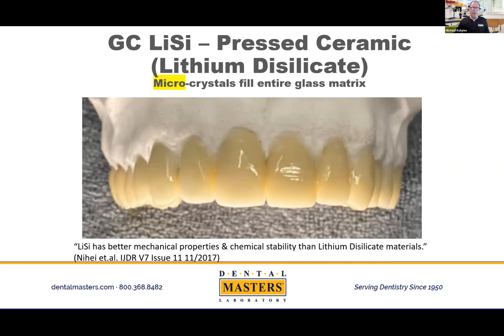This is a competitor to Emax. It's the GC Initial LiSi, lithium disilicate. It's different than Emax in that the microcrystals for this material fill the entire glass matrix that leads to a better degree of vitality, a better light refraction. And in addition, according to what was published by Nihei in 2017 in IJDR, this material has better mechanical properties and better chemical stability than two other lithium disilicates compared in the study, which were the Ivoclar and the Shofu lithium disilicate materials. So I encourage you, if you've not tried LiSi, whether it's with us or another laboratory, please ask about it, try it.